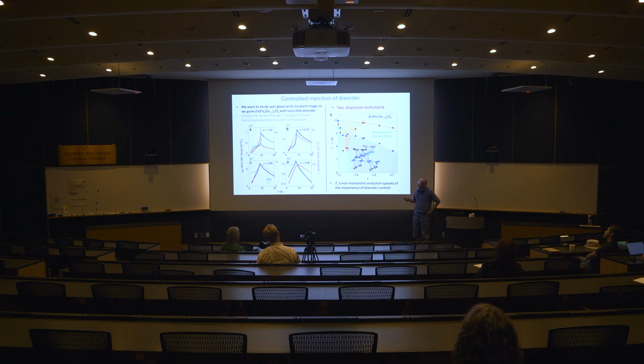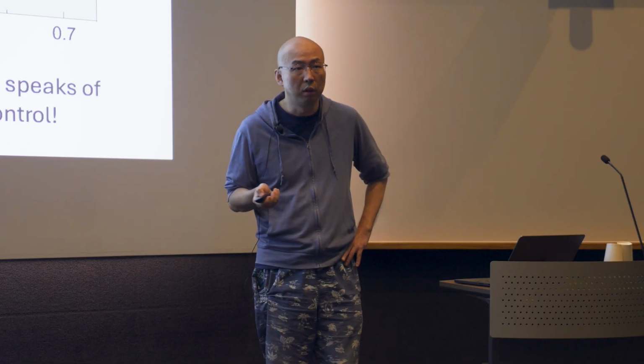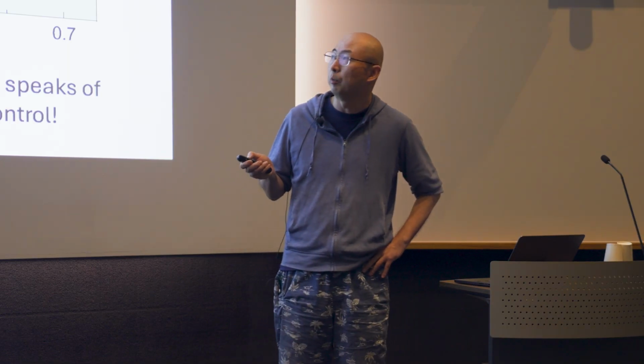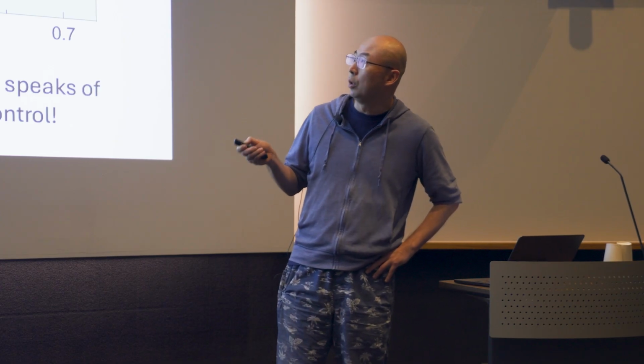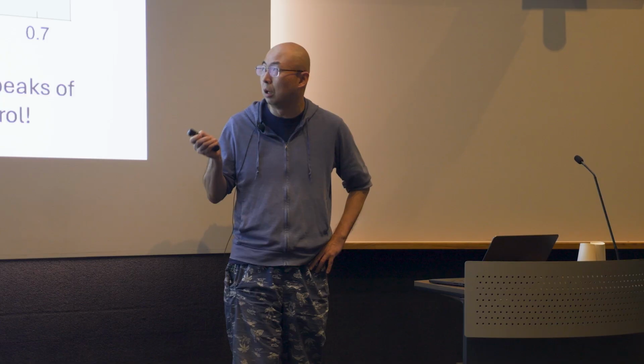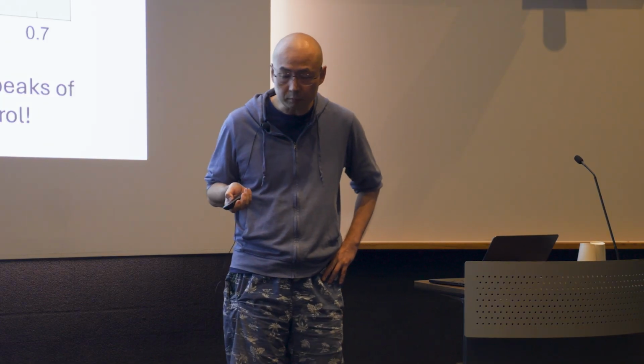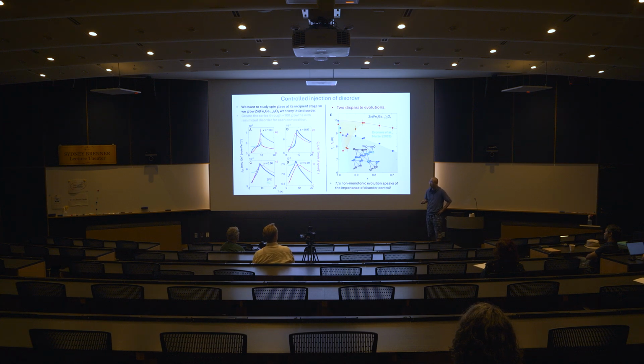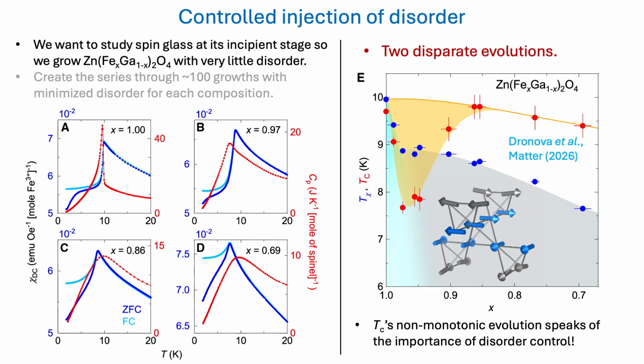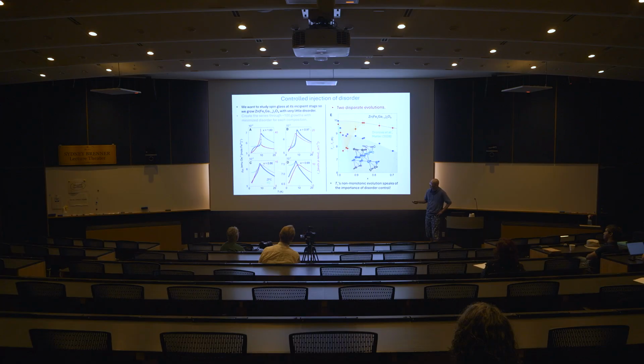This is actually a very challenging experiment. At the beginning, we don't know how much disorder is too much disorder, so you have to be very careful for each composition. Eventually, you need to put lots of effort into minimizing the amount of disorder. For each value shown here, we need to do a very careful growth parameter check. It took us more than 100 growths to get this. However, it's very interesting: you measure the heat capacity, which is the red curve here, and the blue curve, which is the magnetic susceptibility. In the pure sample, they almost match, with a small difference. But once you start doping, they have large differences.